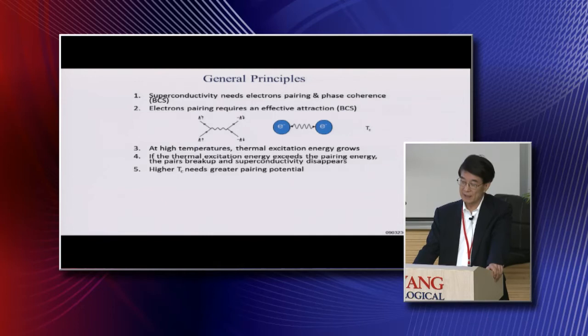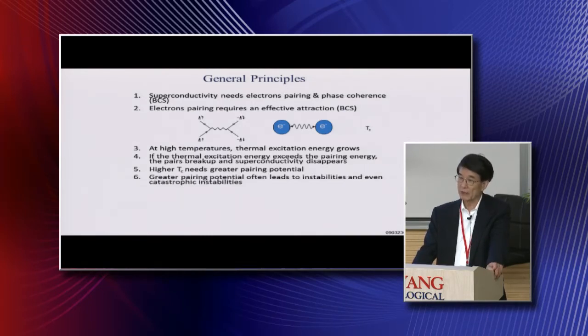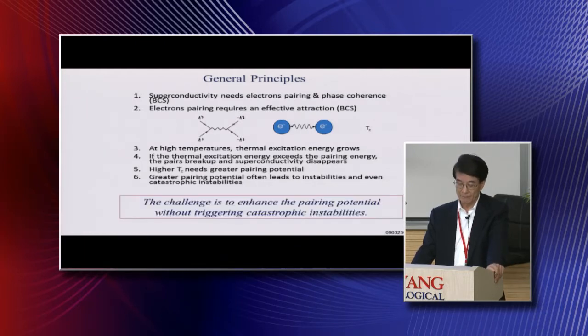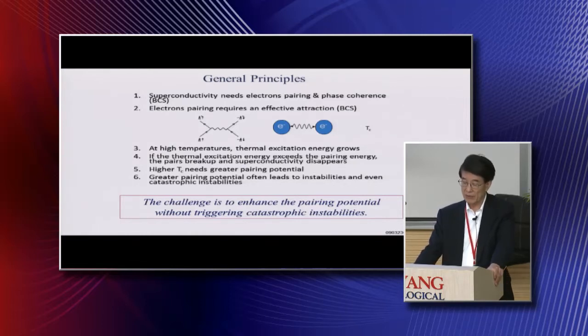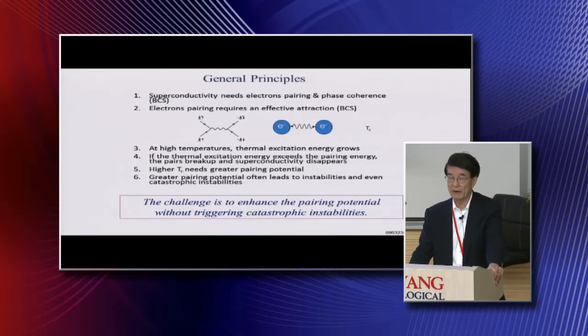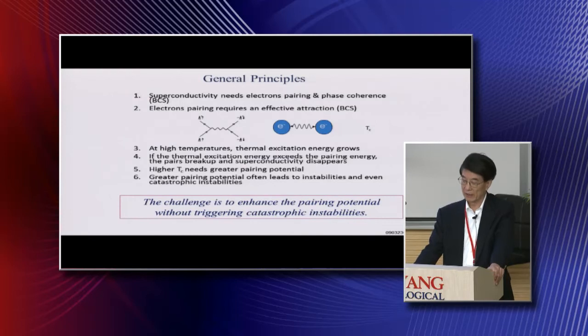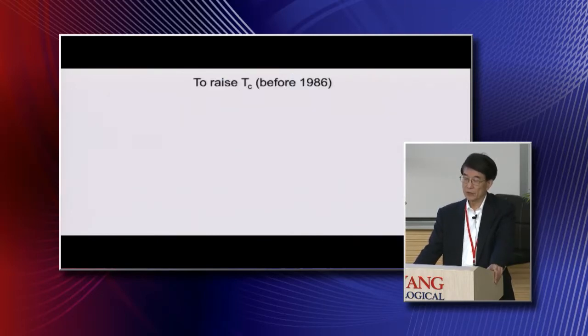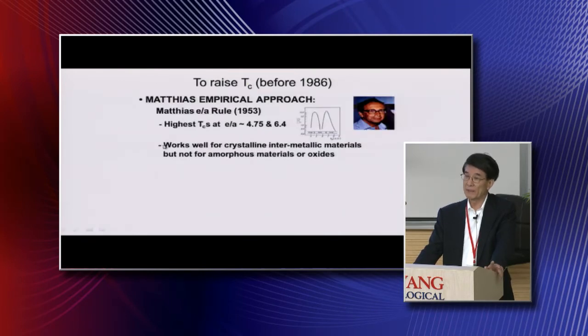So higher TC needs greater pairing potential. But unfortunately, when you have a greater pairing potential, it can induce some kinds of instabilities and even catastrophic instability. In other words, the material may not even exist. So the challenge to raise the TC is to enhance the pairing potential without triggering catastrophic instabilities. So to raise TC before 1986, there are two basic approaches.